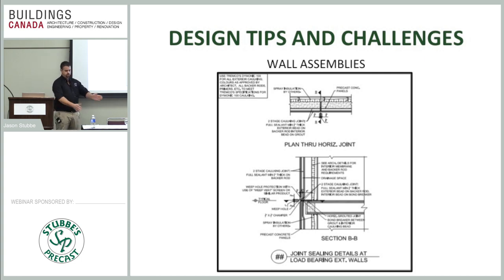For interior finishing, the typical process is: once the wall is in, the stud framer comes in, leaves a 1-inch gap, installs a 2.5-inch or 3.5-inch stud depending on the owner, runs all electrical, mechanical, and plumbing, then spray-foams over top just before drywall. For exterior panel coating, we use a BASF coating applied at the same time as caulking — about $2.00 to $2.50 per square foot installed. It's a two-coat process available in smooth or sand finish; the sand finish looks like stucco, and there's also a staining option.